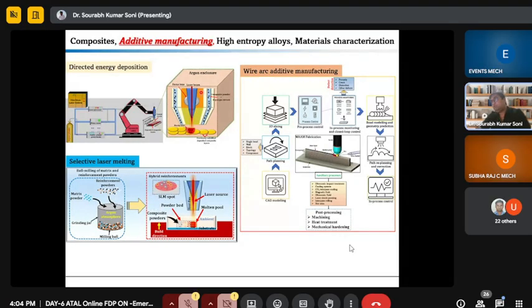So before processing DED and SLM, you can follow the reinforcement pre-processing to get the uniform dispersion of the reinforcement. Specifically in nanoparticles, because carbon nanotube or graphene particles are highly agglomerated. So you must use some ultrasonication or ball milling technique to de-agglomerate them. This is the WAM process in which we are using either matrix or reinforcement in the form of wires. So before using in WAM, we must produce that wire, composite wire, to fabricate the composite.